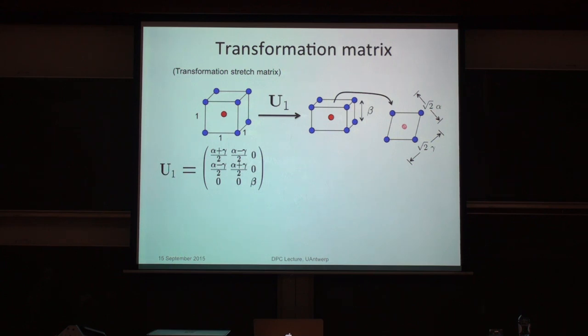So for different phase transformations, we measure those matrices by measuring the crystal structures and lattice parameters by X-ray measurements of those two phases. Actually, alpha, beta, and gamma are eigenvalues of that matrix, but I need the ordered eigenvalues. So I'll rename them lambda 1, lambda 2, lambda 3, conventionally. And lambda 2 is going to play a special role. It's the middle eigenvalue of this matrix. Okay?